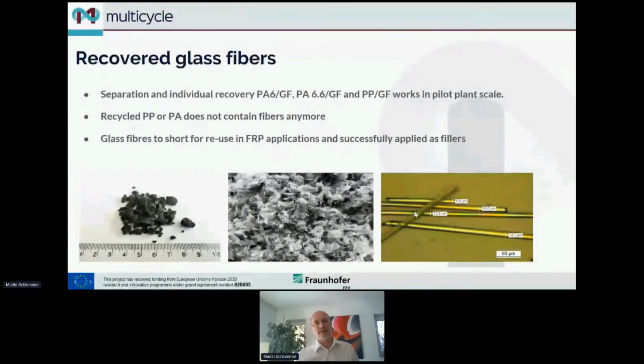So the separation of the glass fibers from PA6, PA66, and PP works quite well in pilot plant. The recycled polymers do not contain any fibers anymore. And for the glass fibers, here you see how they look in such a process. They are unfortunately too short for fiber reinforced applications so far. So this is why we had no chance to bring it back into glass fiber reinforced materials in this project. However, what we tried to do successfully was to mill that down to have a glass fiber filler material, and this could of course be used as an additive in glass fiber filled materials.